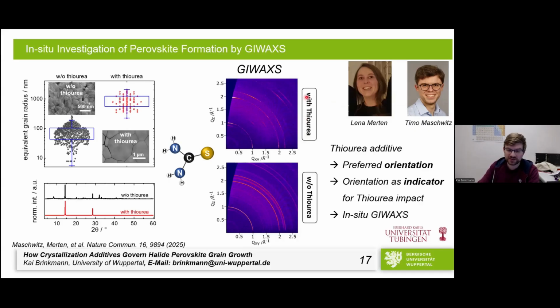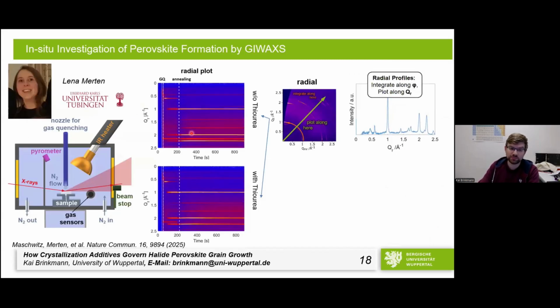We have one sample without thiourea, one sample with thiourea. We've deposited it. In the end result, we get without thiourea a very randomly oriented perovskite with more grains. With thiourea, highly oriented. So this is what you see here in these more localized scattering patterns, that it's very well oriented. And then we probed what actually happens during the formation.